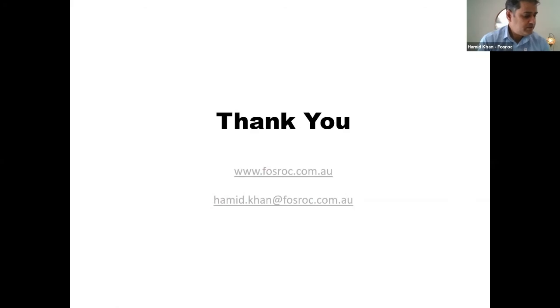I tried to be on time here, but just to summarize again, in specifications, compressive strength should not be the only criteria for the selection and specification of repair materials. Today, specifications for concrete repair mortars are becoming increasingly comprehensive. They should definitely cover all the necessary parameters to ensure the durability of repaired areas. I would say cementitious repair mortars must exhibit low shrinkage, low permeability, and good compatibility with the substrate. And the second part comes in the operational and application part.